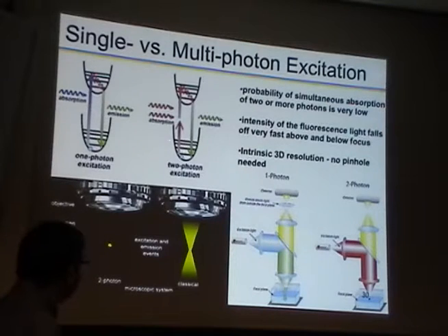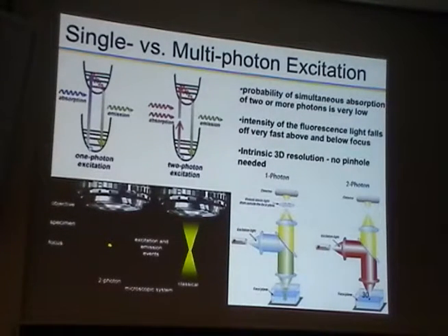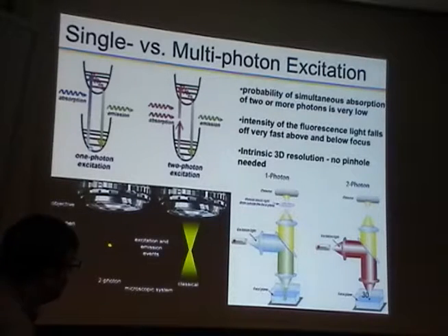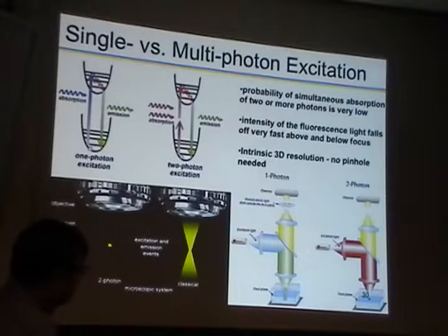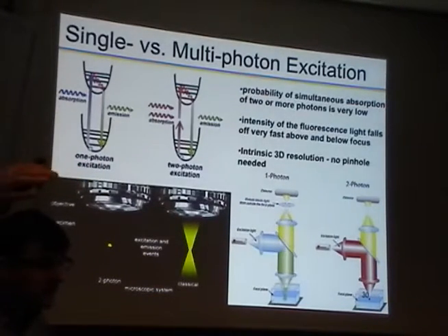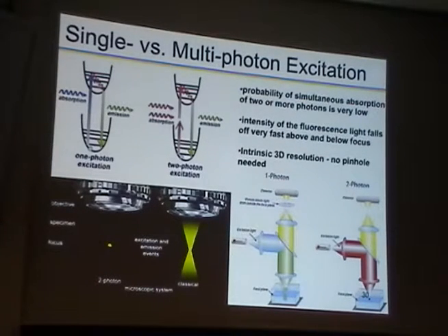And so in order to be able to do this type of imaging or microscopy, we will be exciting the samples using red or infrared laser light, as depicted in here, and we will be detecting the light in the visible part of the spectrum where all detectors work quite well. So this detection scheme is somewhat different from one-photon excitation, when we typically excite at a short wavelength and detect fluorescence light at a longer wavelength. When we use multi-photon techniques, two-photon excitation in particular, we excite the molecules with a longer wavelength laser light, but detect at shorter wavelengths. And this is quite useful because